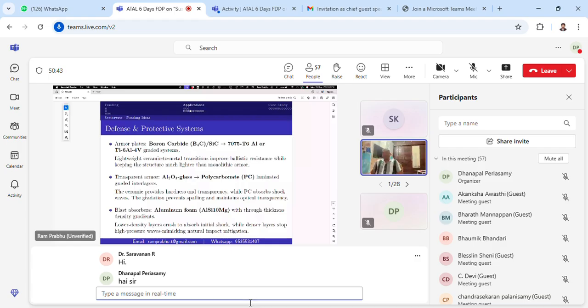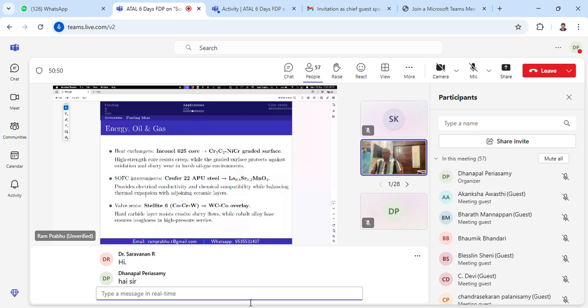Then energy sector or oil and gas sector, if you want to work in functional graded materials, I have put 3 applications. One is a heat exchanger, another one is solid oxide fuel cell interconnects, third is the valve seats. So in all the cases you can see, you will have a high temperature alloy, steels or superalloys, in the core. On top of it, you will have ceramics like carbides, chromium carbide, or lanthanum strontium manganese oxides, or tungsten carbide cobalt overlay. So the idea is again a hard casing, tough core. The tough core will have high temperature properties also.